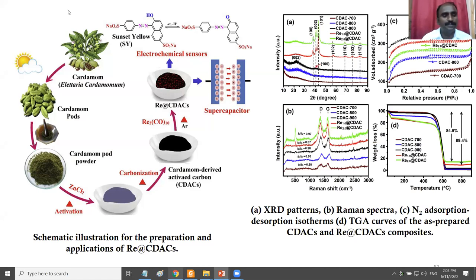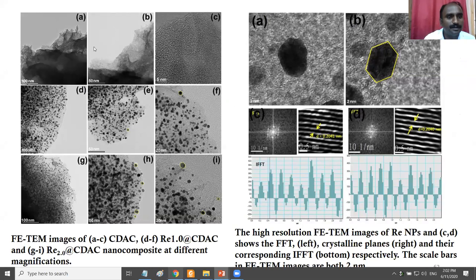In this case, you can see the cardamom-derived carbon, only the carbon material. It has a highly porous nature and high porosity. It also has several carbon layers, the graphitic layers, arranged in a manner. And this is the bare carbon without any metal doping. Next are the TEM images of the rhenium-doped carbon material.